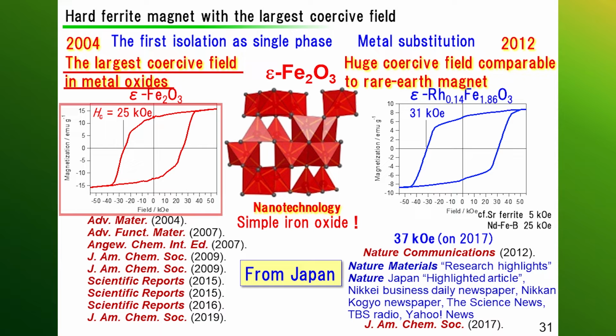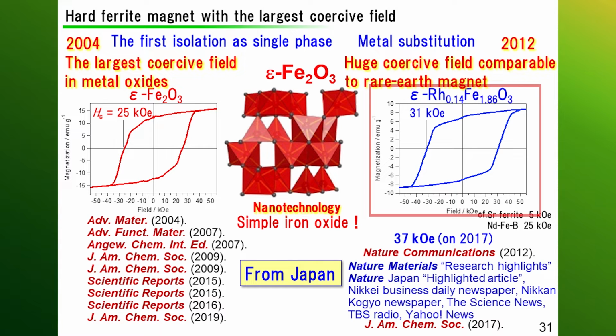We also know that a part of this metal iron can be substituted, and in the case of rhodium substitution, the coercive strengths reach even a higher level of 31 kilo-Ørsted. This is how a high level of coercive field strength was achieved with simple iron oxide.